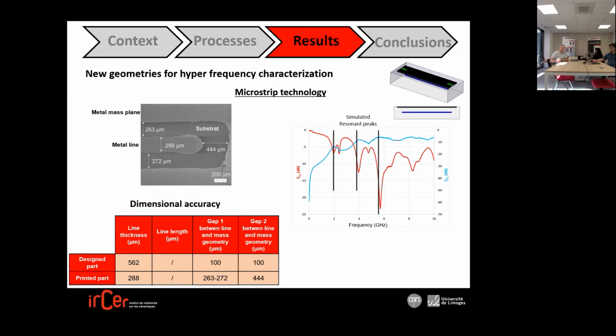Another part that has been presented here is of the same type. You can see the metal shape that has been printed, the difference between the design and the printed part, and in the right graph, you can see the real response of the component, and with the three black vertical lines, the theoretical simulated resonant peaks. As you can see, there is a little offset between the simulated resonant peak and the real one, but the two appear, and the component has a behavior that could be predicted by the simulation.